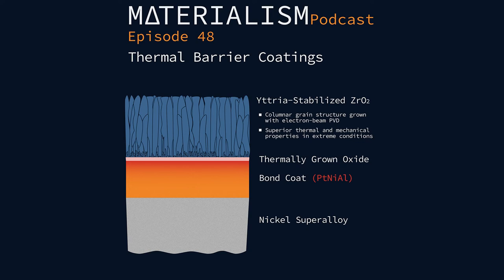And so on one hand, you're like, well, shoot, we'd love to add as many defects as possible. And there's a problem here. If you look at the phase diagram for this, you run into a problem. If you add too many, if you have too much yttria in the zirconia structure, you actually will push it over to a regime where it's no longer in the tetragonal phase, right? And if you don't add enough, then it will transform.